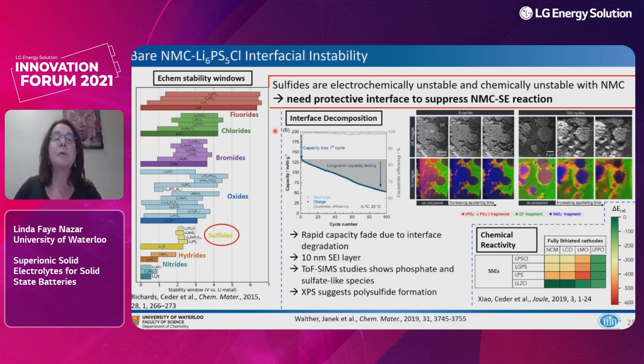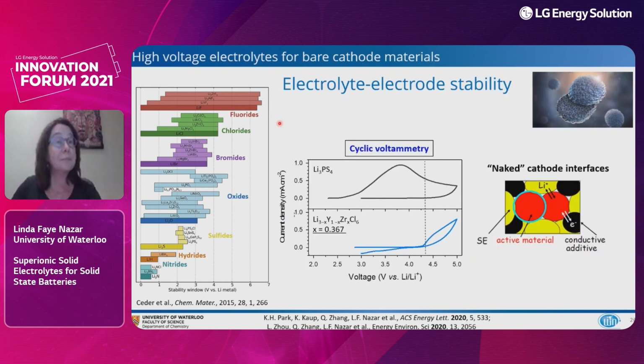And some lovely experiments by Jürgen Janek's group have shown that when you interface these argyrodites with a typical NMC type material, what you end up with is rapid capacity fade because of interface degradation. And this is clearly shown by TOF-SIMS data that show the phosphate and sulfide-like species that are formed. You can see these fragments in the TOF-SIMS. Not to mention some polysulfide formation under oxidative conditions. So in contrast, one can think about halides, because it's also been shown by various calculations, both by Ceder and by Yifei Mo, that they would have a potential window expanding up to about 4.2 volts.